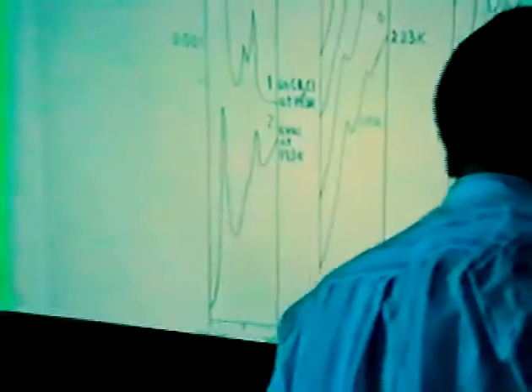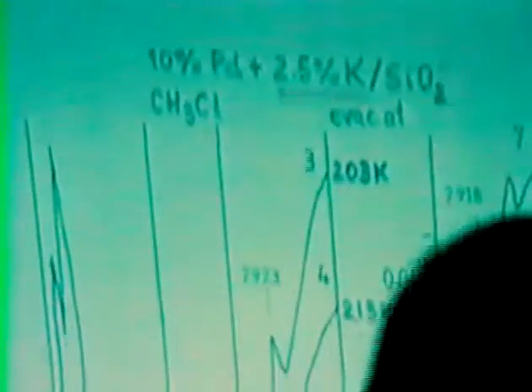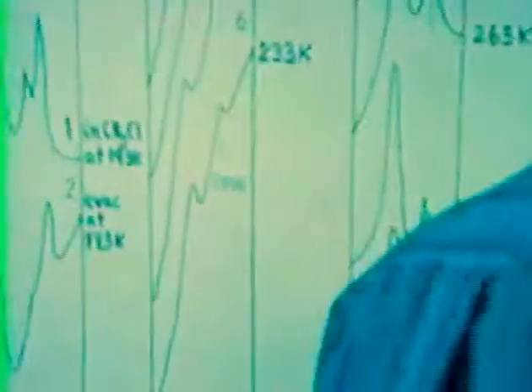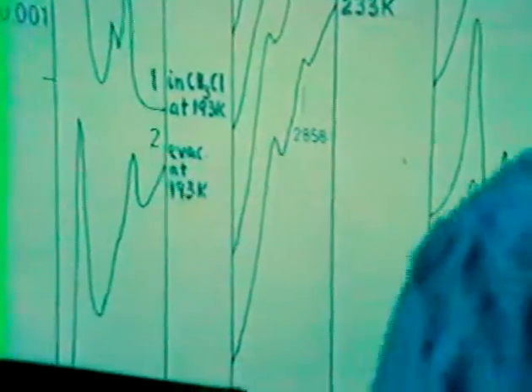In the presence of potassium, the characteristic band for adsorbed methyl appeared at considerably lower temperature, here at 203 Kelvin. This effect can be interpreted on the basis of the classical potassium effect, in that potassium can donate electron to the metal, and the metal donates further electron to the methyl chloride, weakening the bond between carbon and chlorine. Thus, the dissociation of the bond between carbon and chlorine would occur easier at low temperature.